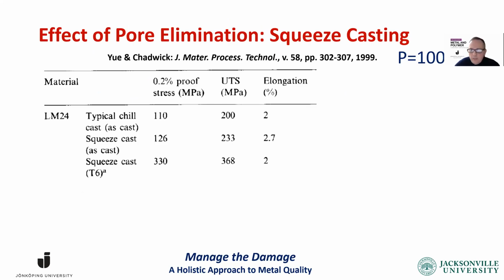Here's some data I found from the literature. It's an LM24 alloy, I think 8% silicon and 3% copper. So when we look at the numbers, yield strength about 110, 126. When it's T6 condition, heat treated, it goes up to 330. Quite a good response to heat treatment. When we look at the elongation numbers, we see 2%, 2.7%.